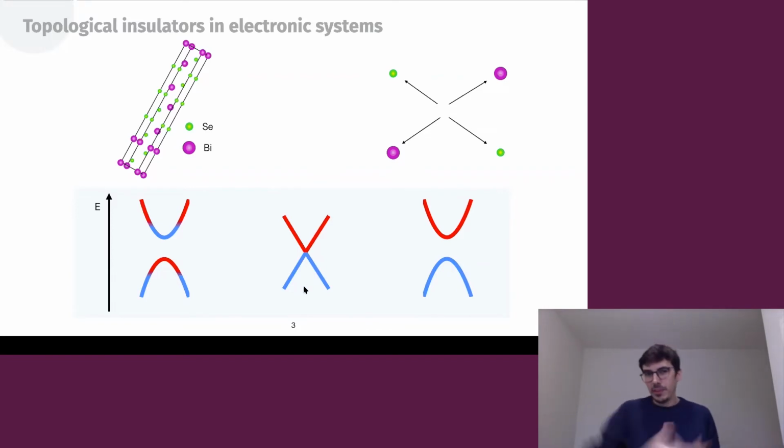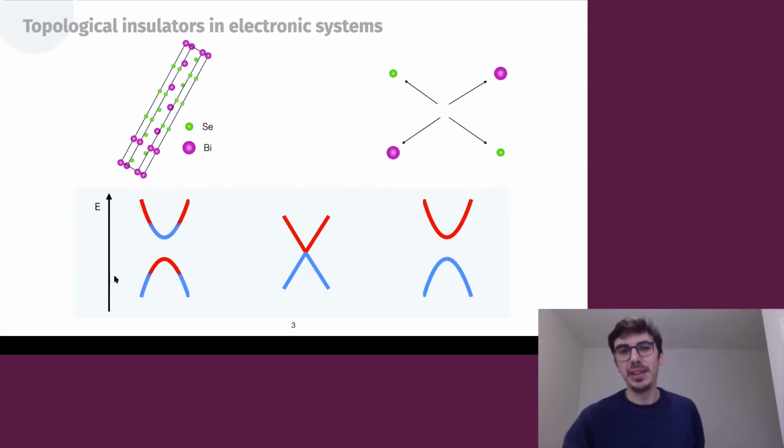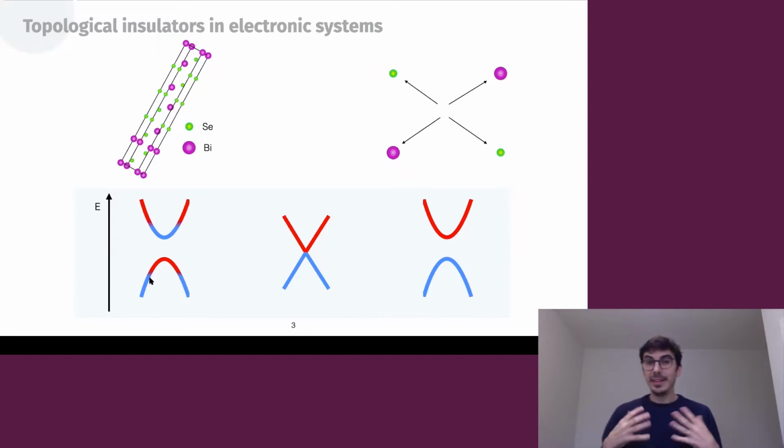So these wave function twists, we can characterize them with topological invariants. I represent them here where I've mixed the coloring of the bands. Sometimes it's called the band inversion. And this places a fundamental difference between bismuth selenide, which we call a topological insulator, and diamond, which we don't. So in bismuth selenide, the wave function has an extra twist compared to diamond.